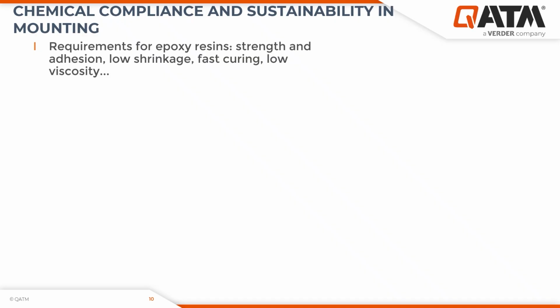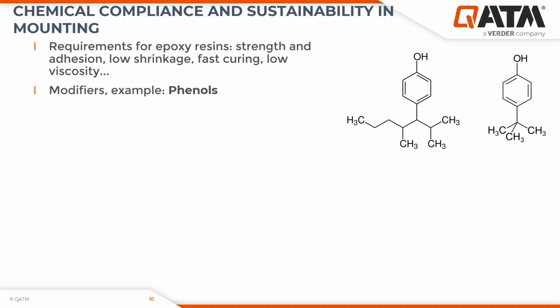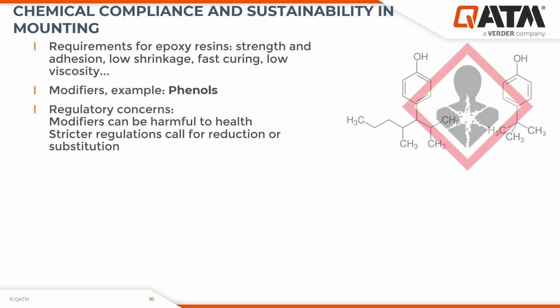And to achieve these properties, resins often contain modifiers such as phenols, which are added usually to the amine hardener component. We have here two exemplary molecules of phenols. The phenol group specifically is the six ring with the OH on top, and without going into too much detail, they decrease curing time and viscosity for way more user-friendly appliance. However, these modifiers based on phenols can be significantly harmful to health, which has raised regulatory concerns.